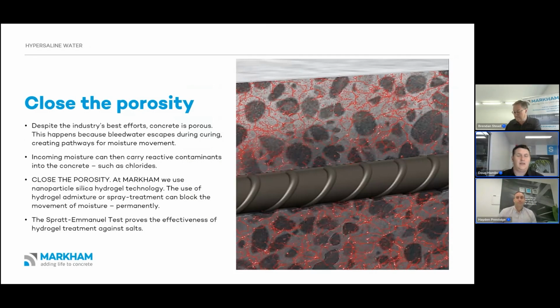Good. Yeah, thanks, Hayden. It's a good overview there of the hypersaline. So I guess first and foremost, it's really important to understand that while concrete looks a solid waterproof material, it's not at a microscopic level. And this is because as the concrete forms, as it cures, the bleed water escapes out of the concrete, and you get left with a porosity or pathways in the concrete that moisture can get back into.